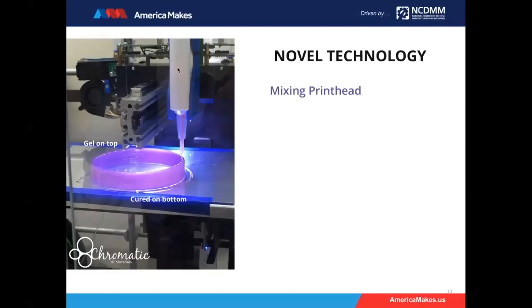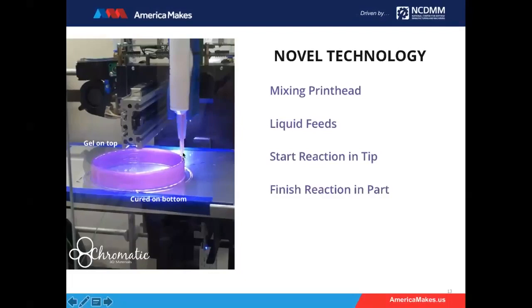So you have liquid components that feed through a mixing print head, and right here we have a static mixer that's about 2 inches long. And in that static mixer, as the two components flow through it, they start to react. So we have those liquid feeds moving through. The reaction starts in this tip, but by the time it comes out, it's only partially reacted, and the reaction is finished in the part. If you look at this part that's drawn here, we have a gel on the top that's partially reacted, while all the way at the bottom, it's more completely reacted.